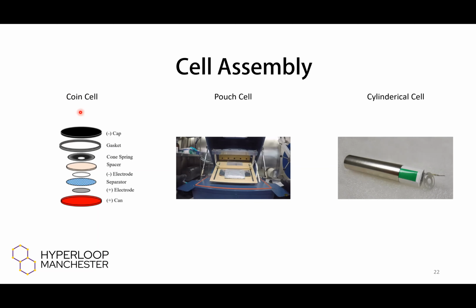Then a coin cell is you've got the cap and the can, and you've got all the materials inside. You also have a spring and a spacer inside, and these are then crimped. So the outer edge of the can is folded around the top part of the cap, but it's done in a way so they don't short circuit because of the gasket. And this leads to your watch batteries. And then you've got a cylindrical cell over on the right, which is where you've wound everything up like in the jelly roll, and you slot all of those components in. You make sure you've got contacts down to the tab onto the material so that you can contact one of the electrodes. And I'll talk about one of the innovations there in a second. But that's it. It's basically just slotted into a can, and this rim is also crimped, so it's just folded over in on itself to seal the cell.